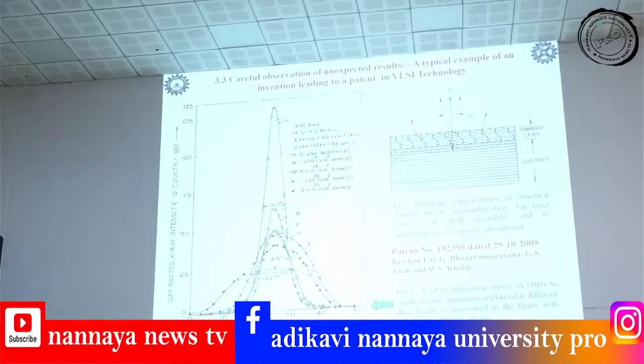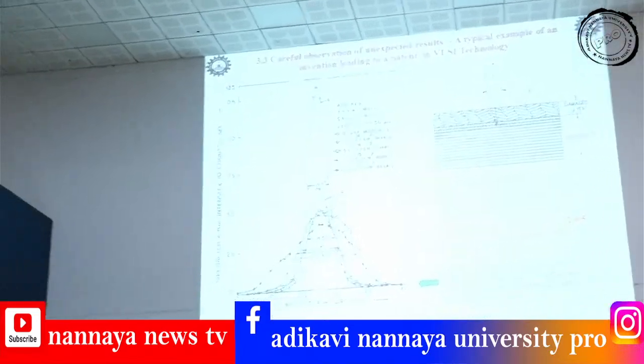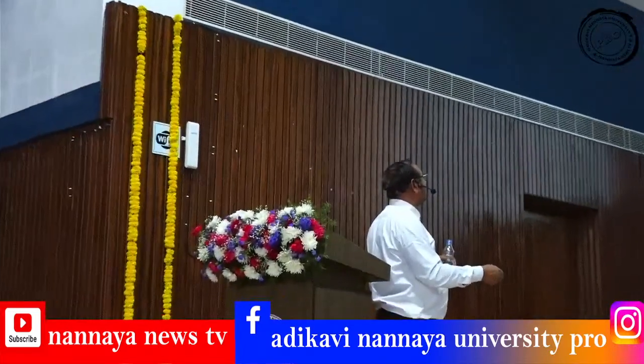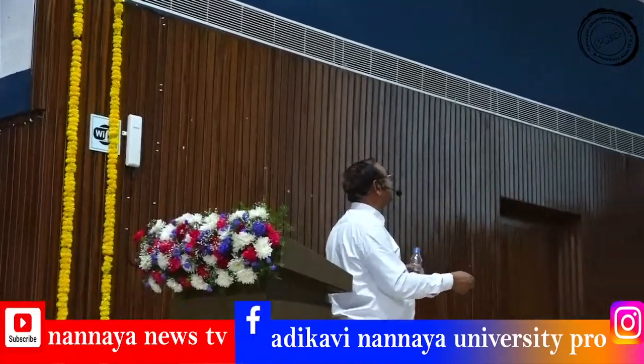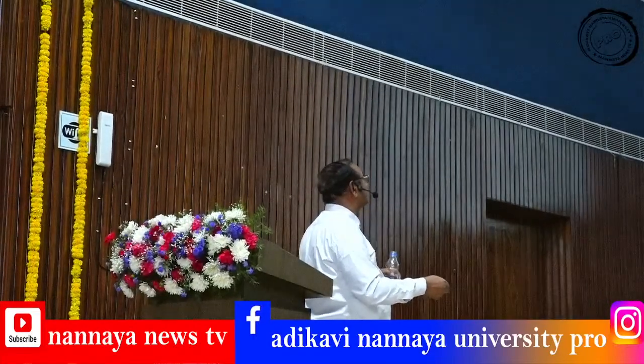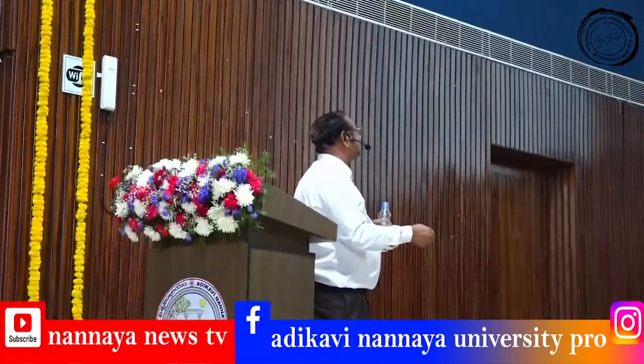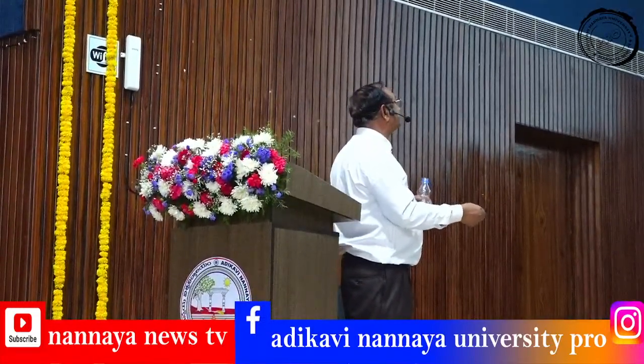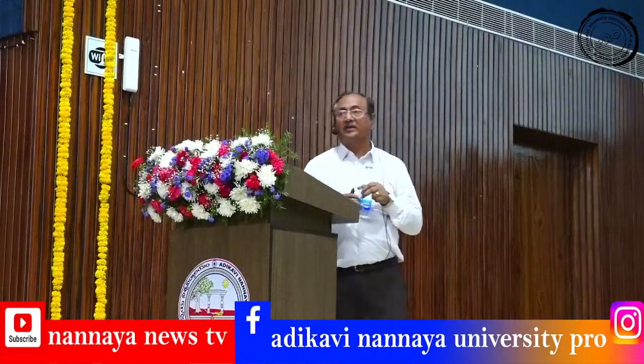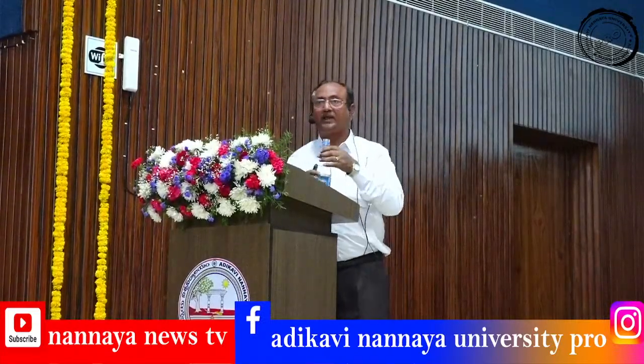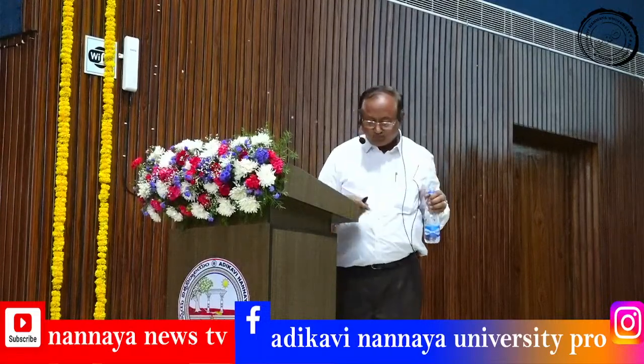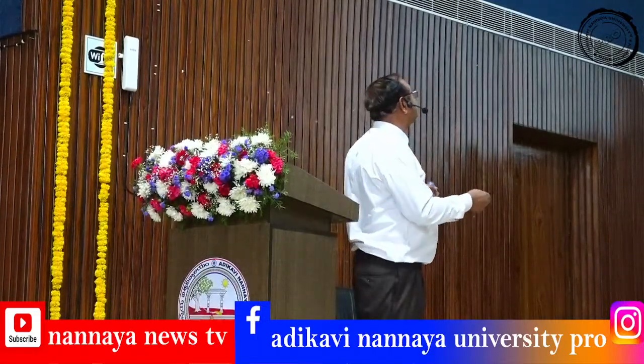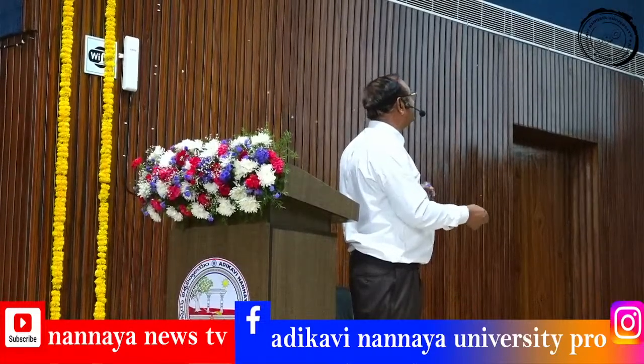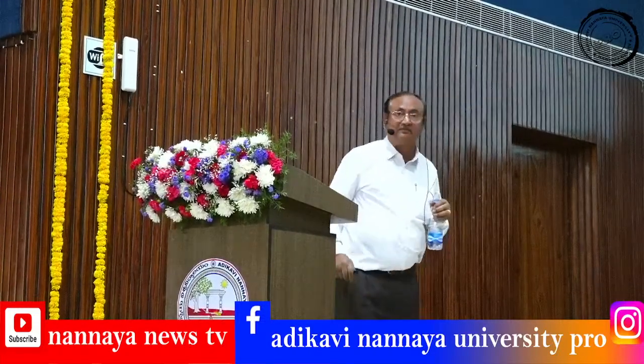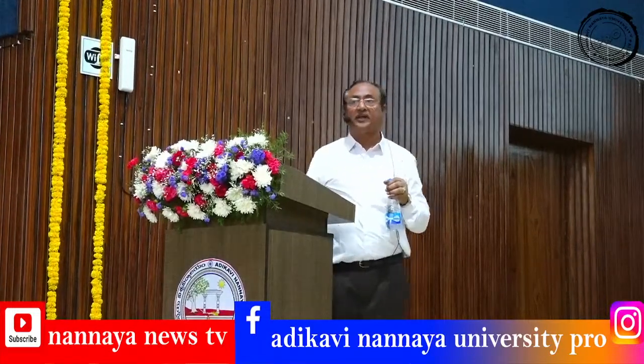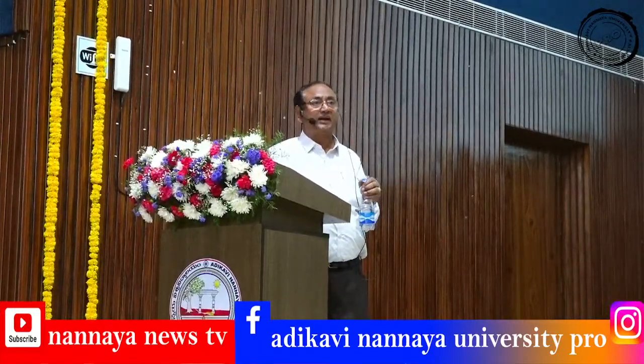So while doing the experiment, these are the diffraction curves. This is for a blank wafer, and these are recorded at different doses. As the dose goes on, the quality or the crystallinity is deteriorating. So this half-width is increasing; the half-width tells the same thing. While doing the experiment, I found that this curve is never altering, but these are getting sharper and sharper with time. So then I thought there is something going on, annealing at room temperature itself.